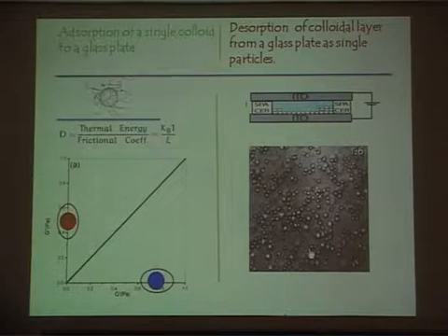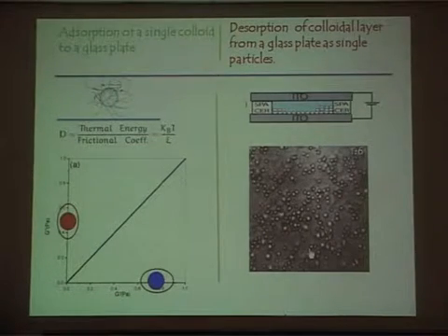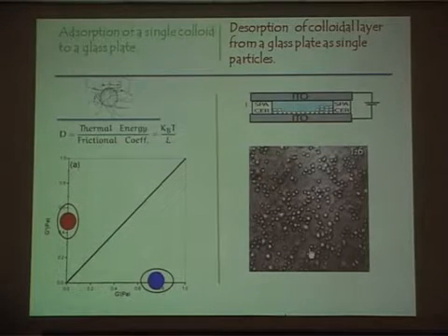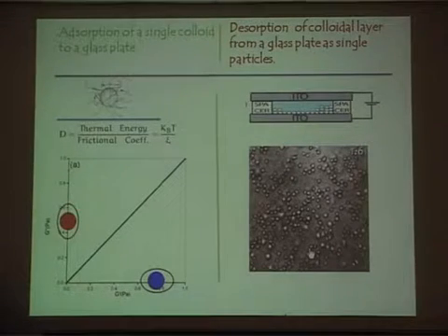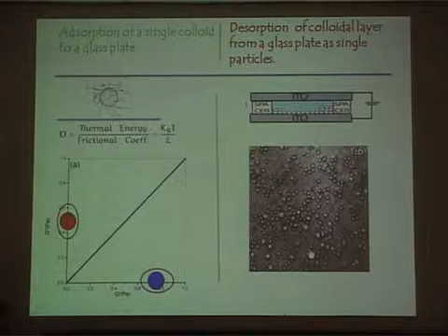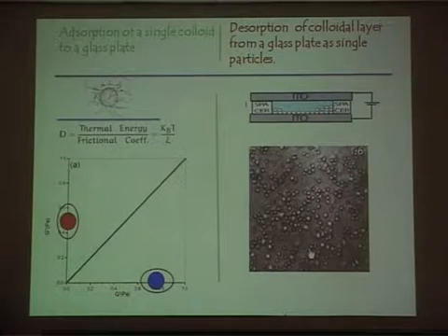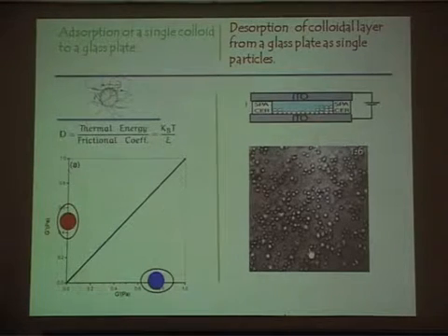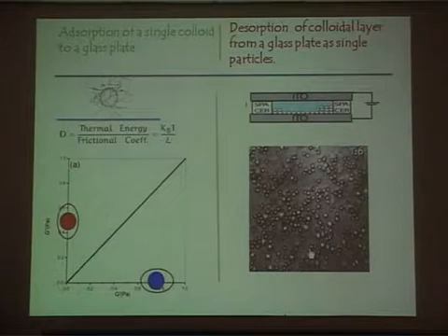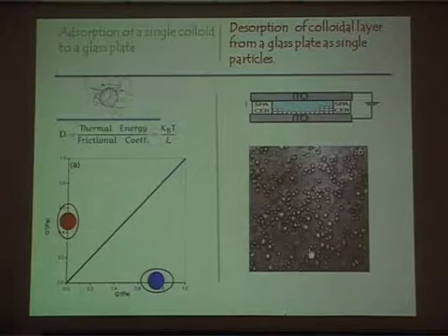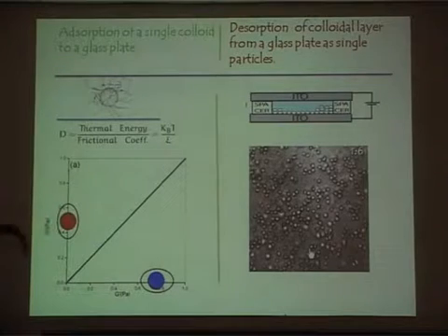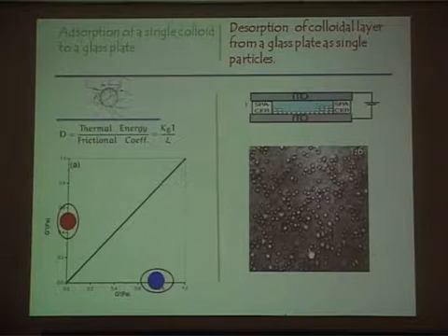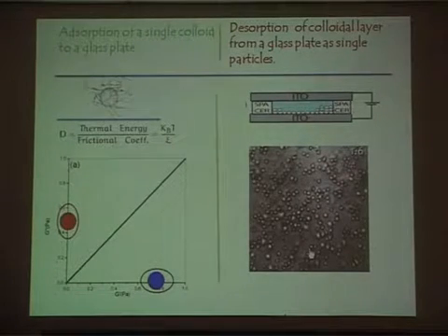Now, I'm going to look at the opposite part of it. What I did was I swept the stress. I took the particles, applied an electric field. These are dipolar particles. The moment I apply an electric field, there's an induced dipole moment upon them, so they experience a stress and want to align in this direction. That's the reason why the particles leave this plate. Suppose I had not swept the field, but went to a critical field and just waited there. Then I would have seen creep events. The particle would still have gone without my increasing the field.